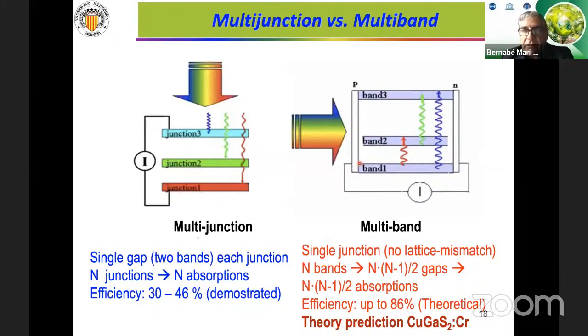And when dealing with multi-band, you can theoretically use only one intermediate band, or you can use n intermediate bands. According to the theory, the efficiency can be up to 86% if we use a lot of intermediate bands. Theoretically this is possible, but in practice it is not easy to control the energy levels in a material.